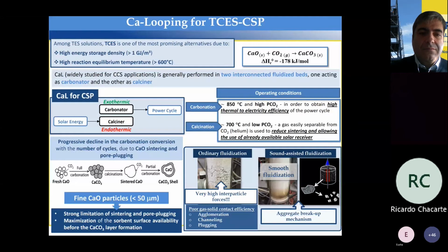However, fine particles belonging to group C of Geldart classification of powders cannot be fluidized under ordinary conditions, since interparticle forces prevail over hydrodynamic and gravitational ones, thus leading to agglomeration and channeling phenomena, which in turn hinder the reaction efficiency due to the poor gas-solid contact efficiency. Therefore, in order to overcome these strong interparticle forces, externally assisted fluidization can be used.